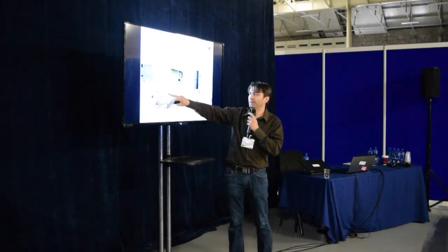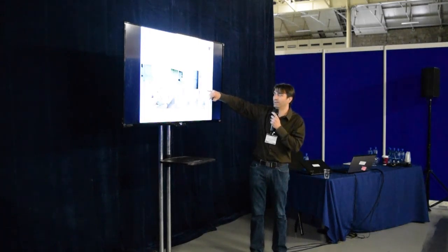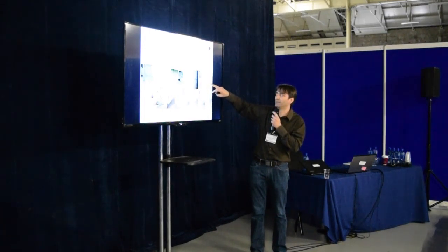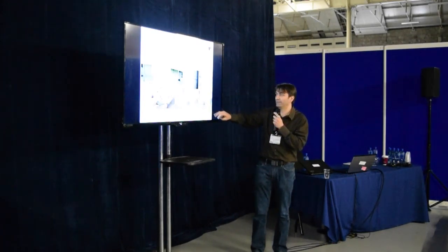Now here we have an example of a test sample with bacteria microcapsules, and we can see two samples, one with capsules, one without. And we can see after healing that the sample without the bacteria had no repair, and the one with bacteria repaired the crack completely. So it's very effective. Our test site we have as well in the Netherlands, this pavilion in Breda.